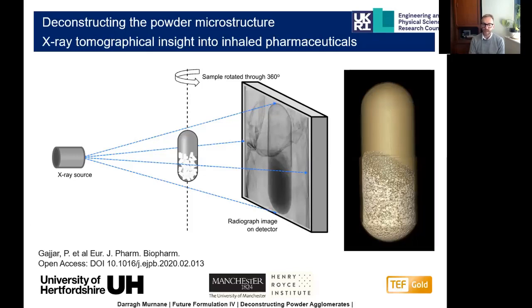So starting with the X-ray source, sticking a representative sample, for example powder in a capsule, into our X-ray microscope, building up those radiograph images by rotating the capsule, we can build up a three-dimensional image of that powder, and then we reconstruct this model of a powder.